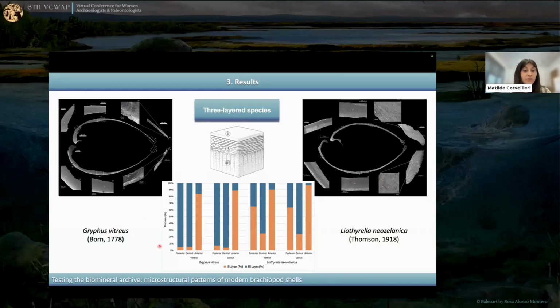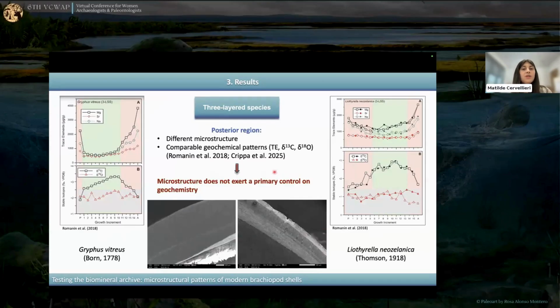The two species actually differ in their posterior region, since in Gryphus, it is quite comparable to the central region. And so we have still this huge block of tertiary columnar layer, whereas in Liothyrella neozelanica, the secondary layer is still dominating over the tertiary, and this microstructure is more complex, and the columns are intercalated between the stacks of fibers. So we have seen that the two species differ in the posterior region for their microstructure.